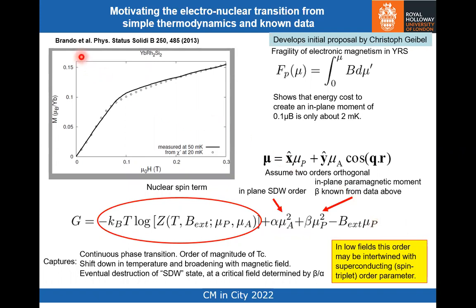So what this data that I keep referring to, at 50 millikelvin, the growth of the in-plane moment as a function of magnetic field tells you, when you integrate it, is the energy cost to create an in-plane moment of about 0.1 μB here. And if you use this data to calculate that energy cost, it's only 2 millikelvin.